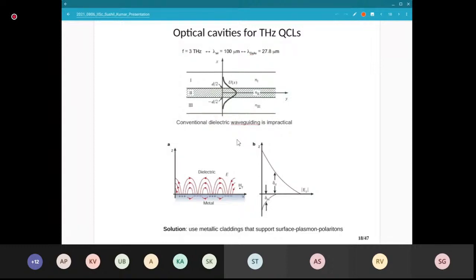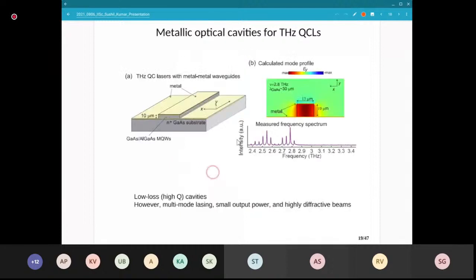And the reason that works is because metal layers allow propagation of surface plasmons. These are the modes that are hanging on to the metal-dielectric interface and decaying exponentially on either side. And there you can have sub-wavelength confinement. So that's exactly what we do here. In fact, it looks very much like a microstrip transmission line. The only difference is making these is very challenging. So this is how our final laser structure does look.